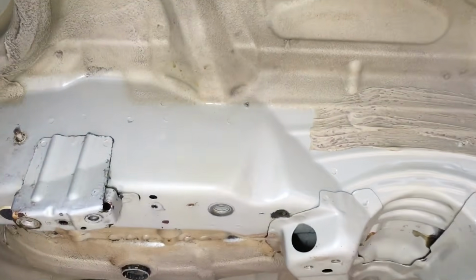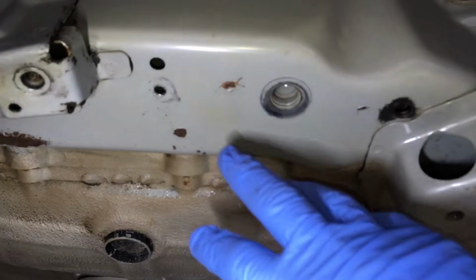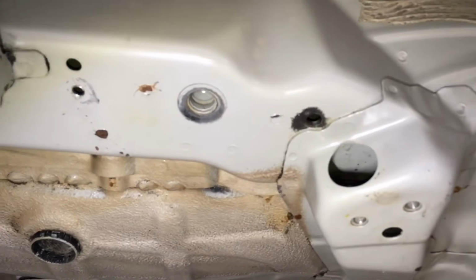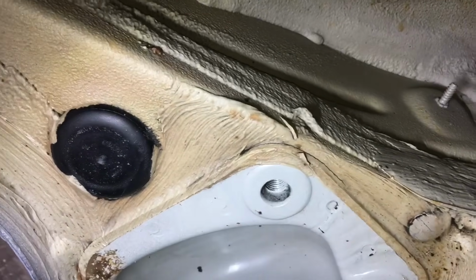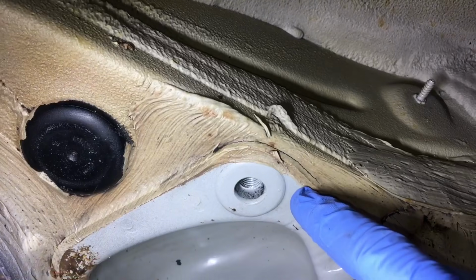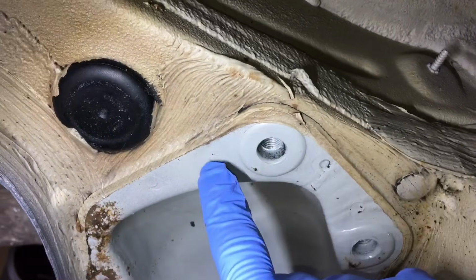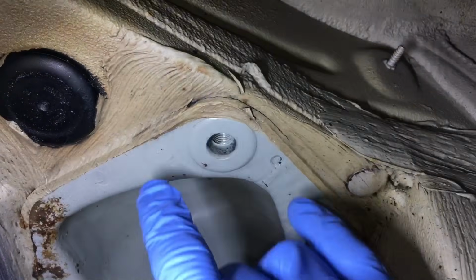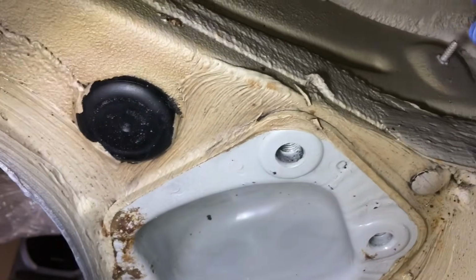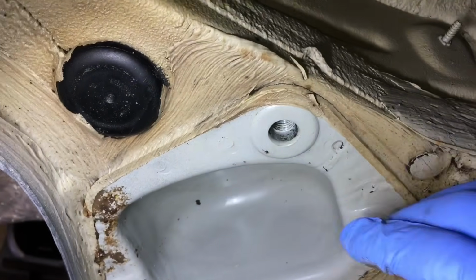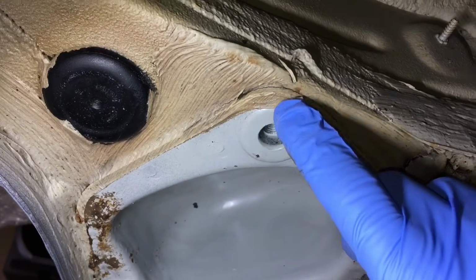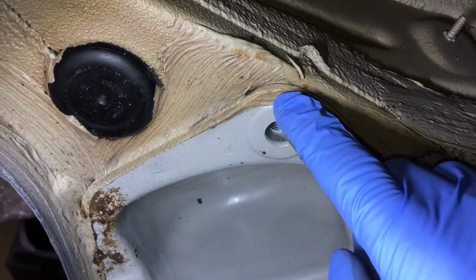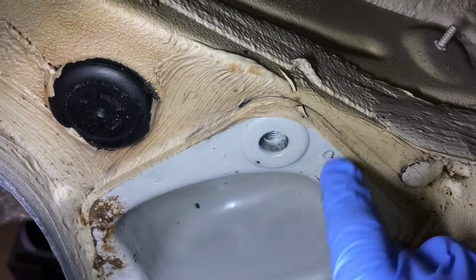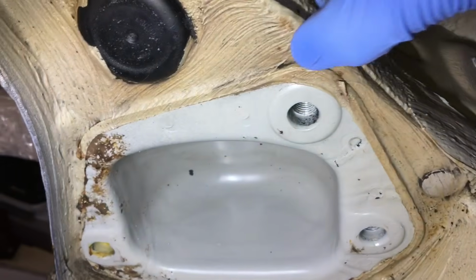So now we can start moving on to the spot weld drilling out, and then also stop drilling the ends of the hairline cracks before we start doing any welding. And interestingly, we've also got a decent amount of seam sealer split here, which is quite interesting. Some cars do suffer with that, and that's just because there's a spot weld there and there, but the bolt point is further past the spot weld point, and the flex on that rear trailing arm pocket joint makes the panel move very slightly. We've never actually seen one break away, but the sealer split in there tells you that there's a good amount of movement. So we'll take that seam sealer out of there, get that back to bare metal, and apply a stitch weld around the very outer point where it suffers most with flex.